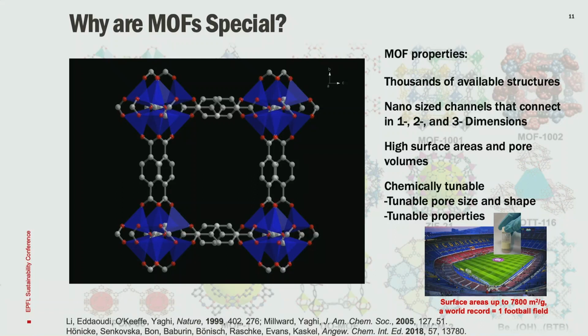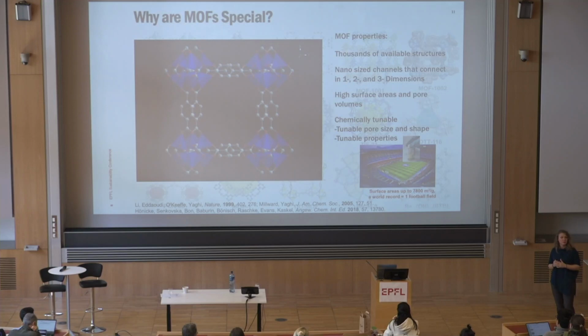There are tens of thousands of structures that have been reported to date with nano-sized channels that propagate in 1, 2, and 3 dimensions. Okay? Pore sizes usually range up to 2 nanometers. However, we're trying to figure out how we can work with even larger pore materials that are on the order of 2, for instance, to 10 nanometers in size. As I've already mentioned, the materials have record-breaking surface areas, and they're highly chemically tunable.